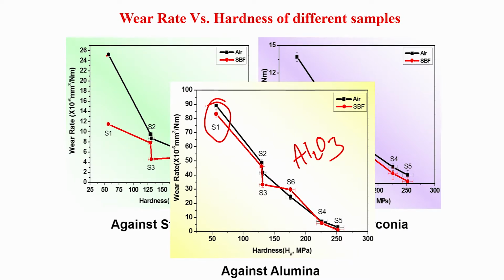What is interesting is that there is, for the pure HDP or unreinforced HDP in case of steel and zirconia, a difference between S1 composite and S1 wear, but here this difference is negligible, or there is not much difference because the error bars overlap. The same is true for S2, S3, S6, S4 and S5. So against the alumina counter body, this is a very interesting or intriguing observation: all the materials experience similar wear irrespective of ambient or simulated body fluid environment. However, there is a difference among the flat materials itself, and a similar qualitative trend was also observed as in case of steel or zirconia counter body.